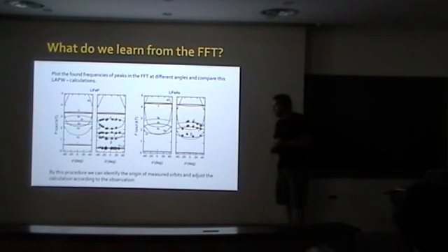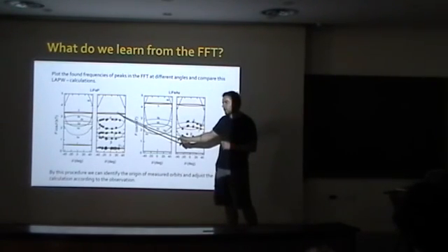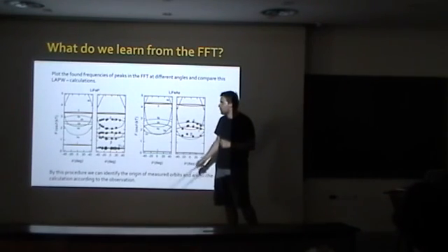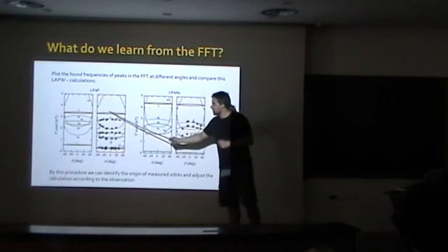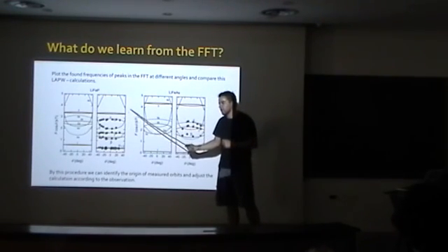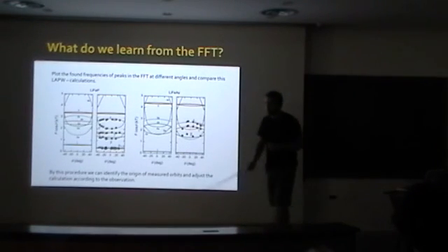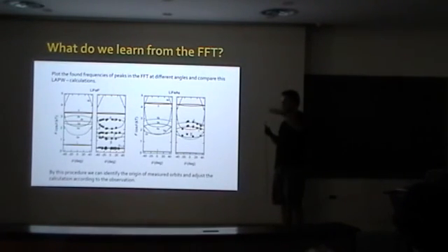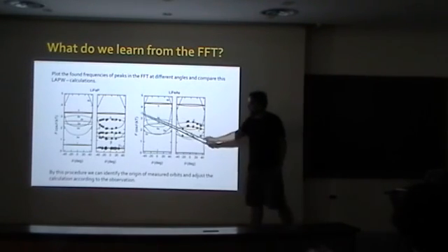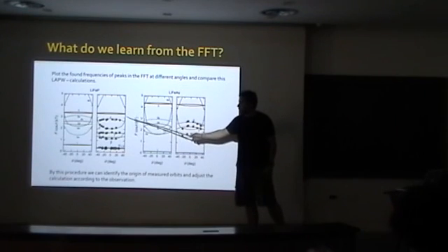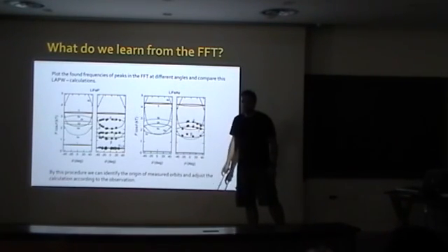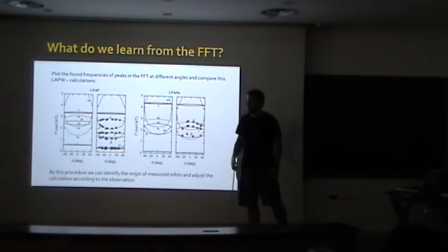So you don't see the red bands in both? We do not yet see the red bands in those cases. On some of those angles, we have a slight indication that it's there, but this depends also on the angle. As you can see, at some points those bands will cross at higher angles. This is the Yamaji angle, where if you look at the angle change, the maximum and the minimum orbit have the same area, and then they add up in oscillations and you get a higher oscillation amplitude. This is the angle that you usually try to look at. In one of the pulses we seem to be quite close, but we have to redo that, because if you do those measurements at pulsed field facilities, you only have a snapshot of one week, and you have to live with the data that you get there.